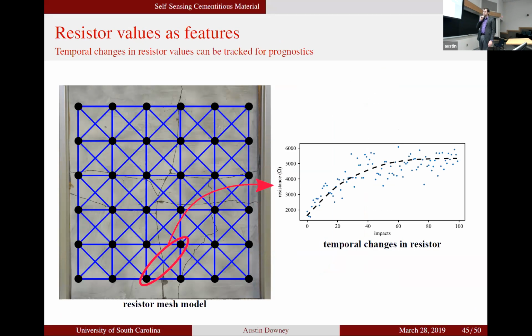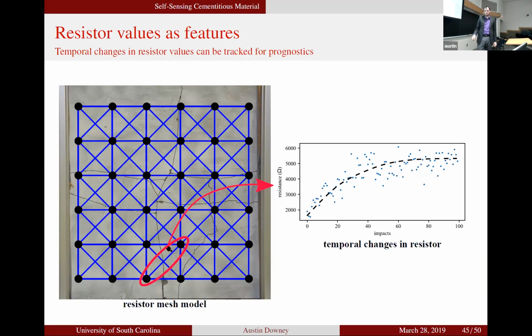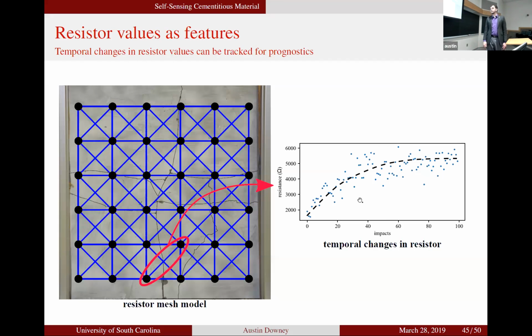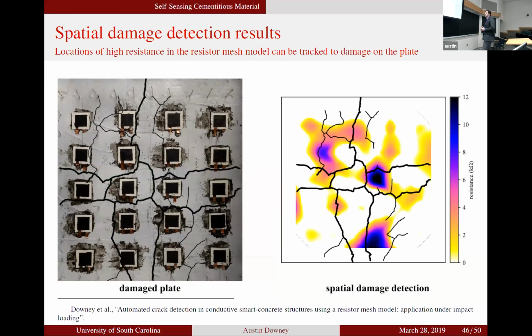Again, we're kind of interested in developing this for prognostic reasons. And so if we take a single element like this element here that crosses a crack that it opens, we can look as we solve this algorithm for each damage point, we can see this increase till about 50 impacts and then a relatively constant increase in resistance. And this actually lines up with what we saw from the experimental data and how that crack opened, right? So this crack starts to open from 0 to 50, then after that, the impacts of the plate really didn't do anything.